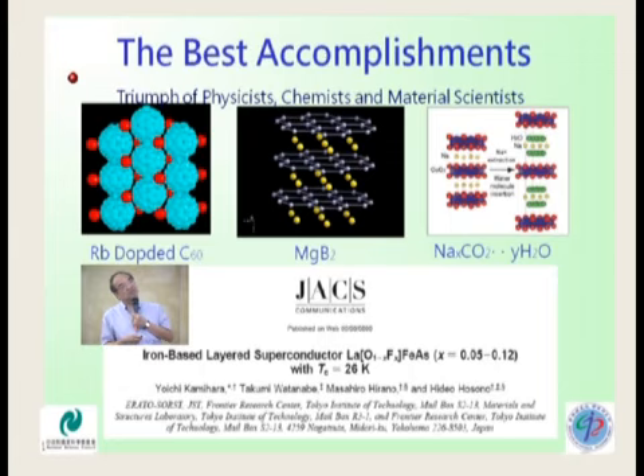Showed in the O here. And there's a group of Japanese again. We found that this kind of material is so amazing. With the parent compound, all right, it is an insulator, non-conducting at all. But when you insert some water between this cobalt layer, then it becomes superconducting.